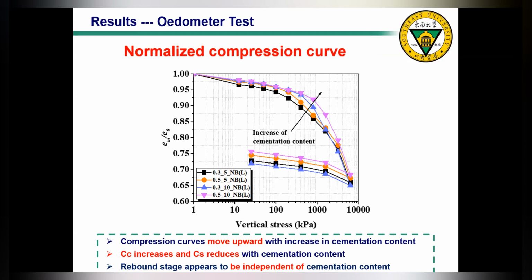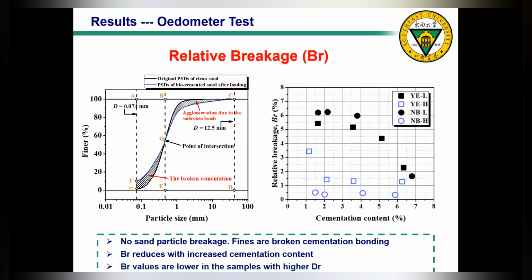And during the oedometer test, we also evaluated the relative breakage. So firstly, I would like to briefly introduce the concept of relative breakage. As you can see on the left-hand graph, this is the typical particle size distribution curve. In this graph, the black one represents the original PSD, the particle size distribution curve of clean sand. And the blue one represents the particle size distribution curve of biocemented sand after loading, I mean, at the end of the compression test.